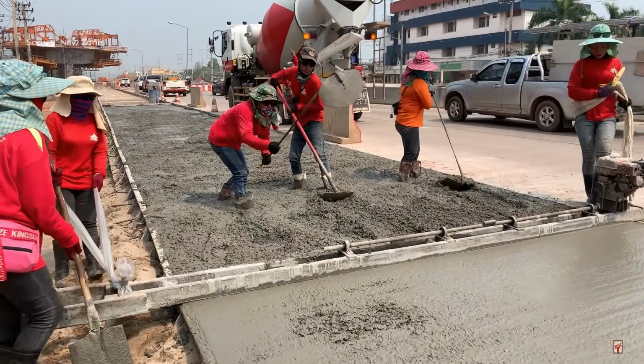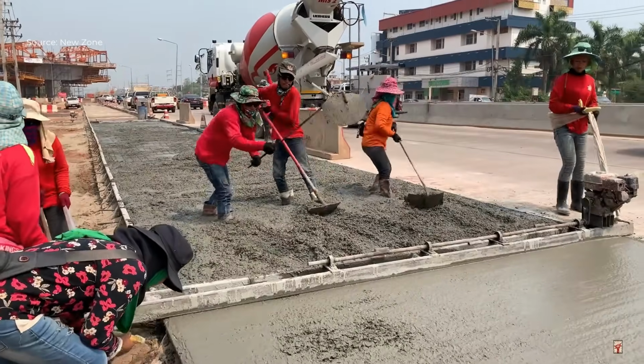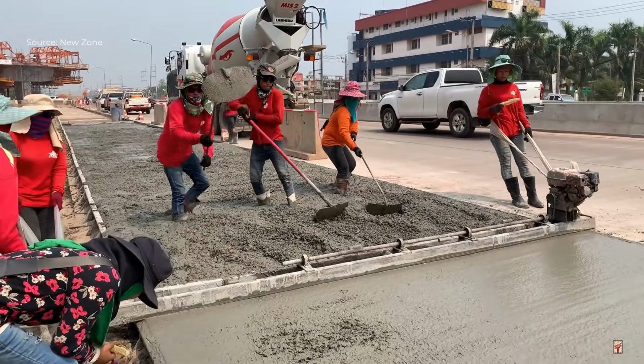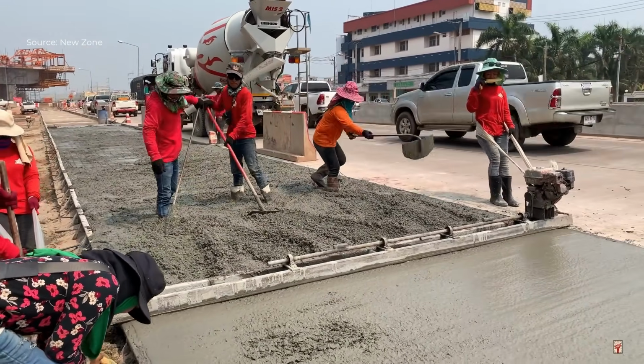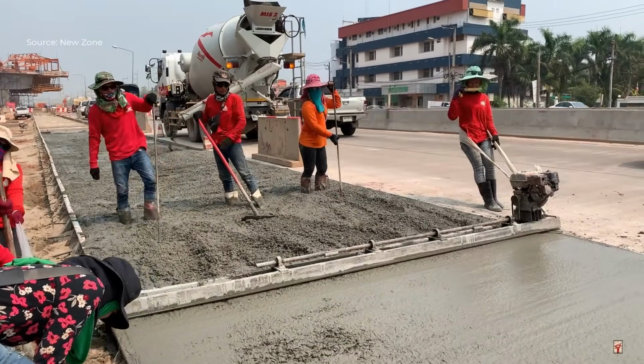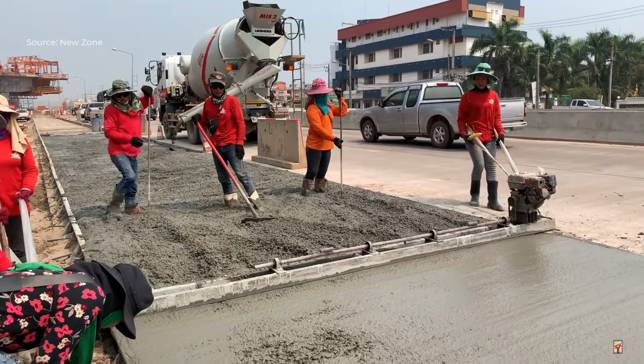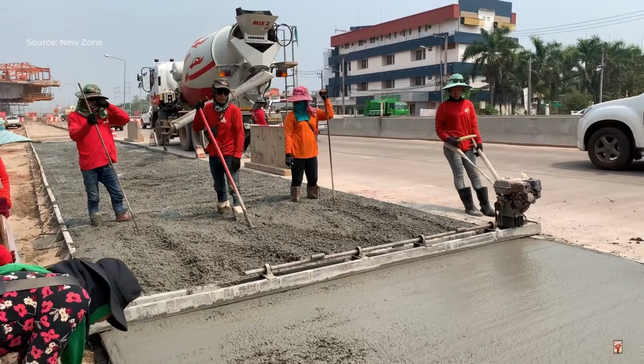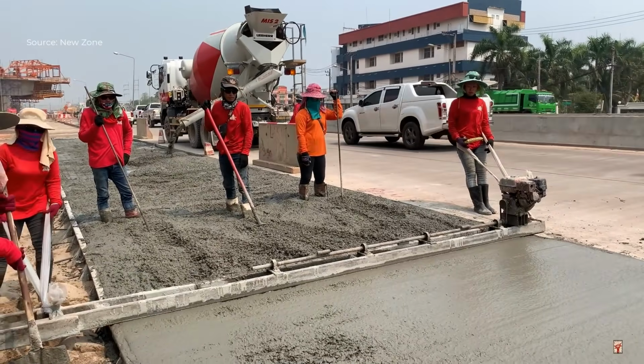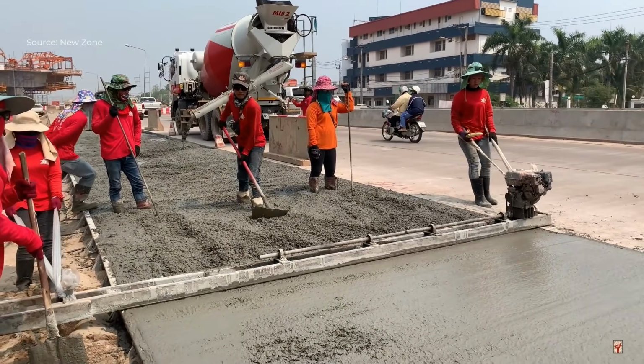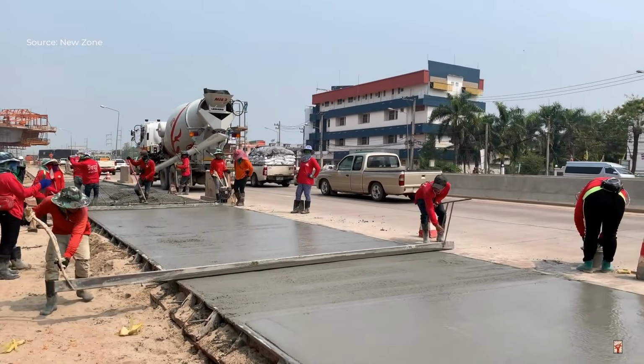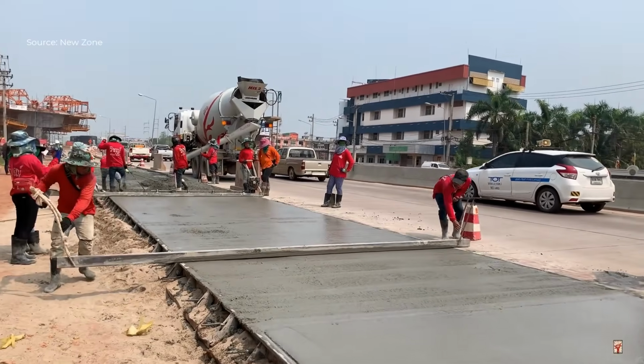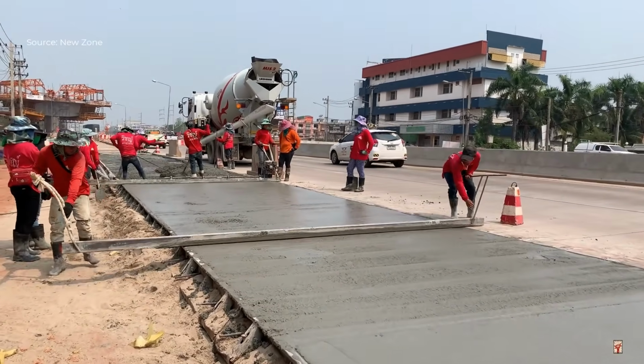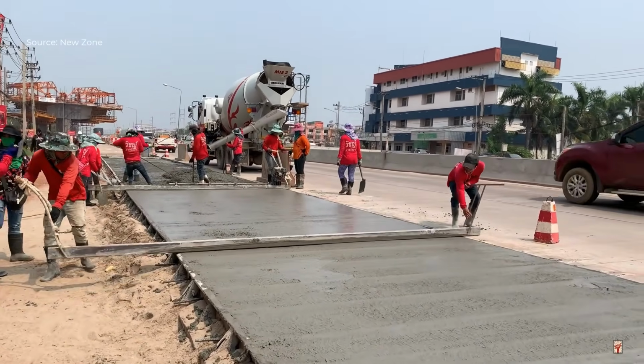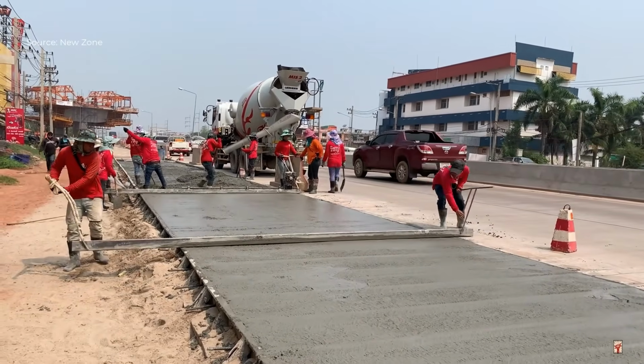After the initial spreading, the crew performs vibration and leveling. A vibratory screed, visible at the front of the working area, moves slowly along the rails, compacting the concrete while striking off excess material. This step is crucial because proper vibration removes trapped air, increases density, and significantly improves the pavement's long-term strength. Behind the screed, workers continue adjusting the concrete surface, guiding the equipment, and correcting any low spots or uneven areas.